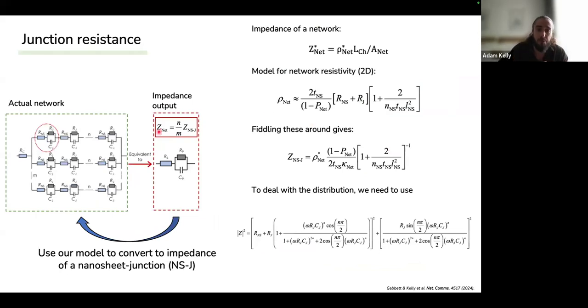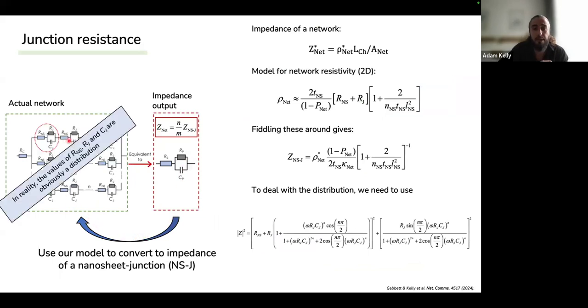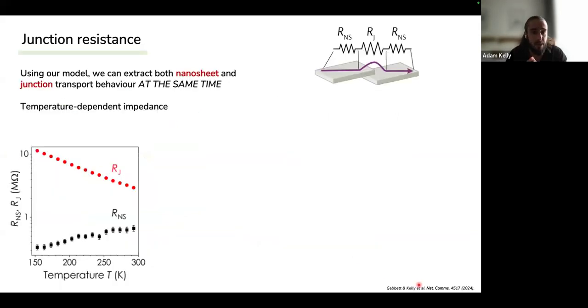When we have our impedance output, we use our model to convert back into the actual network values. This is clearly going to be a distribution. They're not all going to be the same nanosheet resistance and junction resistance. The way we analyze this is with a more complicated equation, but I don't have time to get into it. If you want to find out how we do this modeling, please check out our paper. But this means that we can extract junction resistances and nanosheet resistances. Now, what we find is that we can get the transport behavior of the nanosheet and the junction at exactly the same time if we do a temperature-dependent impedance method.